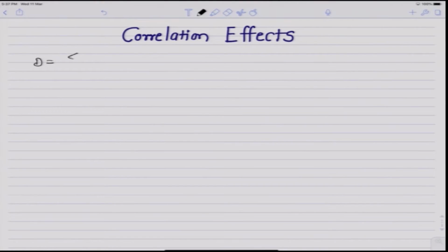Just a recap over the last couple of lectures, we derived the expression for diffusivity in terms of mean square displacement as D equal to average of x square over 2 tau, where x square inside the angular bracket denotes the average of the square of x projections of net displacements of all the atoms, and tau is the small time interval.